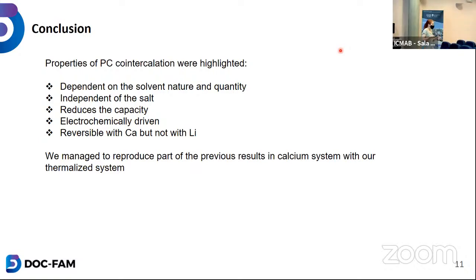So during this study, we highlighted properties of the co-intercalated phase. We know that it's triggered by propylene carbonate. The salt has little to no influence on this phase, but the quantity of propylene carbonate you put in the electrolyte will have an influence on the capacity and on how much co-intercalated phase you will produce. It is not a spontaneous process. You need to have electricity going through your battery to be able to build this co-intercalated phase.